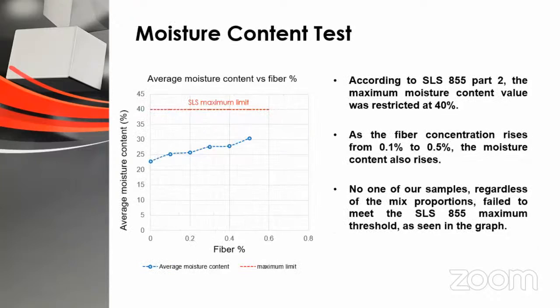Moisture content test. Considering the moisture content test, the maximum moisture content value was restricted to 40% in accordance with SLS 855 Part 2. The moisture content increases as the fiber concentration increases from 0.1 to 0.5, as shown in the graph. The graph shows that none of our samples, regardless of the mix ratios, fail to meet the SLS 855 maximum level.